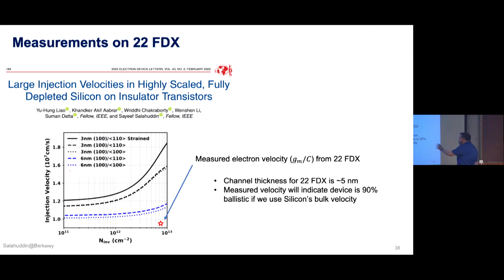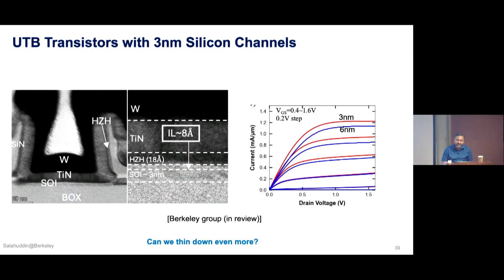Okay, so this showed us indirectly that definitely there seems to be a velocity increase as you thin it down, but we wanted to go much thinner. Al may smile about it, but it took us more than 2 years to build the thinner transistors that we wanted. When we did it, this is a transistor that has 3 nanometer silicon sitting on an SiO2, and then this 8 angstrom of IL, and then our negative capacitance gate stack. If you look at our current-voltage characteristic compared to the 6 nanometer, at 3 nanometer, current actually goes up.